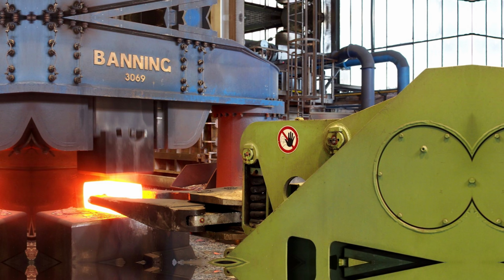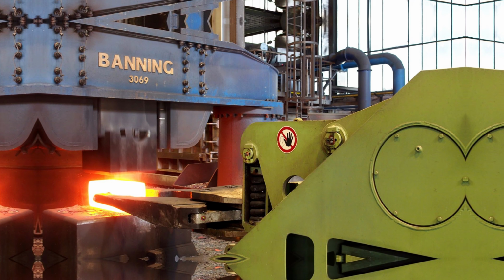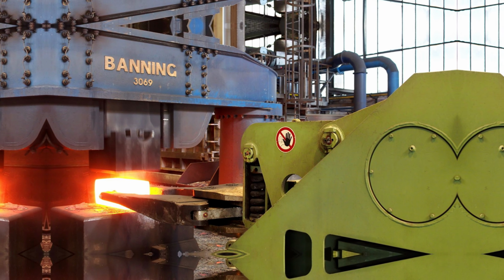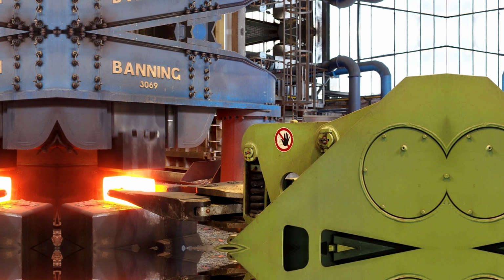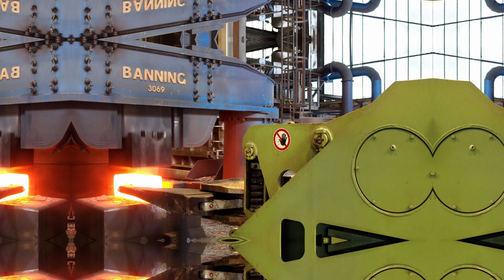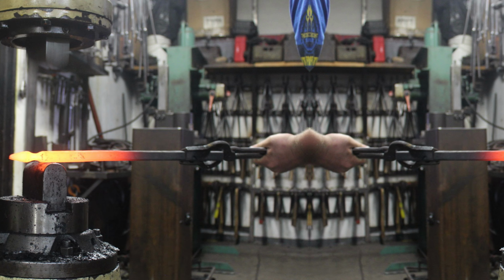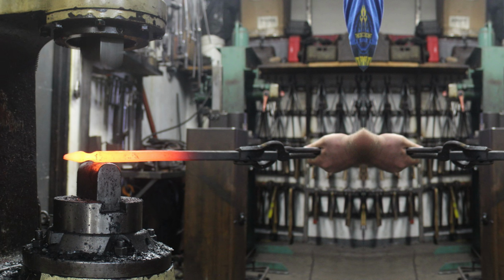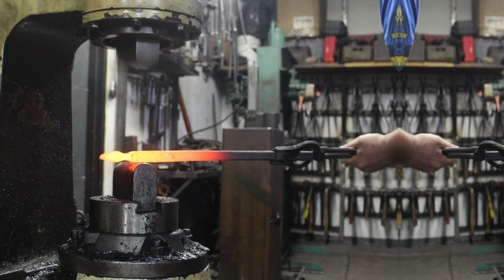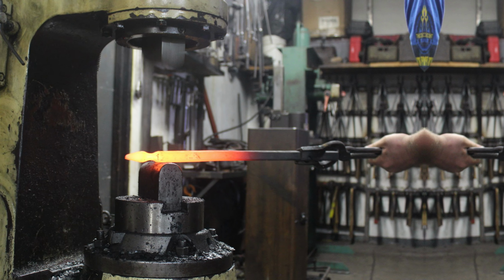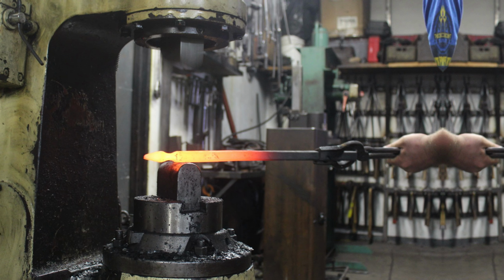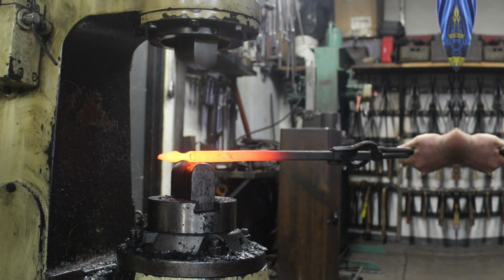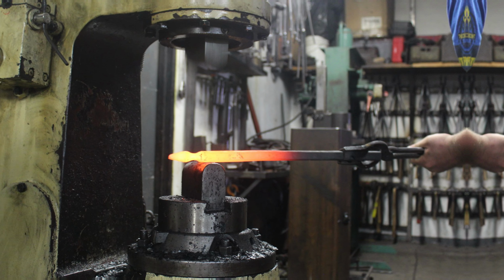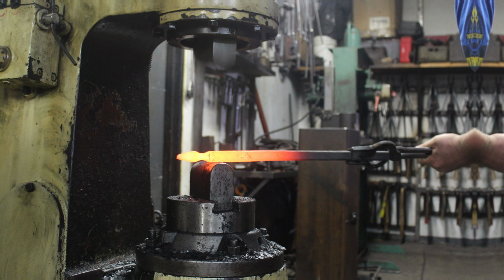But Sarah's metallurgical analysis revealed something unexpected. The bounce mattered. She sectioned samples from both steam hammer forgings and servo press work, etching the steel to reveal grain structure under optical microscopy. The steam hammer parts showed elongated grains aligned in directions that followed the metal's flow during forging, with gradual transitions between zones of different crystal orientation.